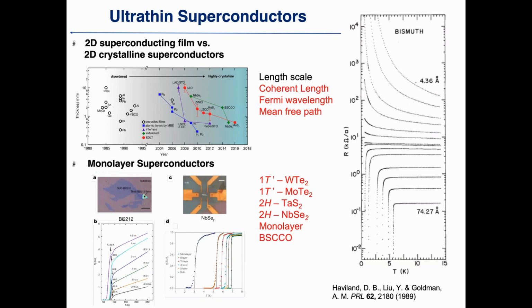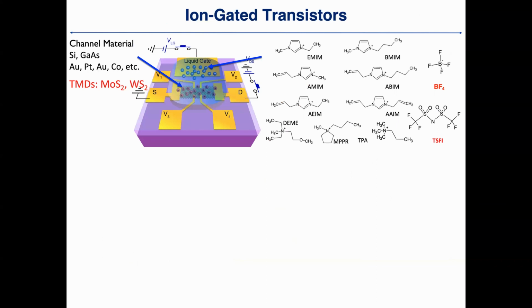Another approach is that we can take one step back, because if you make a 2D metallic system, then most of the time they are not stable. If we take one step back, we can make a very nice system, first as a semiconductor, but then use a technique called ionic gating to turn them into a superconductor. The ionic gating, as I've shown here, is normally made from a conventional transistor, but we replace the gate dielectric with something called ionic liquid. So these are ionic liquids.